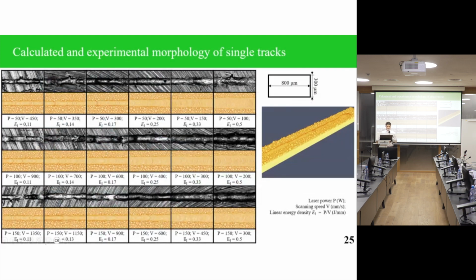Concerning the morphology of single tracks from the top view, we can see that for the lower linear energy density case, the morphology looks the same, but for the highest energy density, in the simulation we received a ripple pattern, whereas in the experimental case we have a bead with a large height on top of the substrate. This is explained by the zero displacement condition that was applied for powder, but in reality we see the denudation effect, when particles nearest to the melt pool are moved into the melt pool and make the liquid domain bigger.